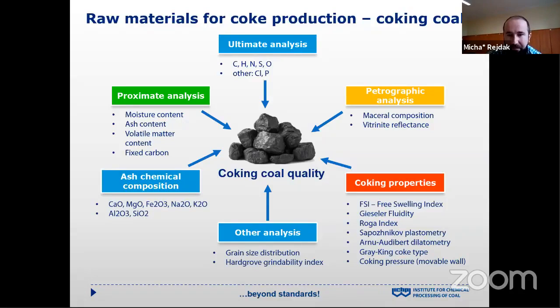The free swelling index is sometimes defined as the crucible swelling number, abbreviated CSN. This is a measure of the increase in volume of the coal when it's heated in a small crucible in the absence of air. The Roga index can provide information on the caking properties of the coal. In general, it evaluates the cohesion of the resulting coke in a drum tumbler when coal is mixed with a fixed amount of a specific anthracite, which acts as an inert agent. And of course, this blend is subjected to a rapid heating rate up to 850 degrees, and afterwards it is subjected to the drum tumbler.